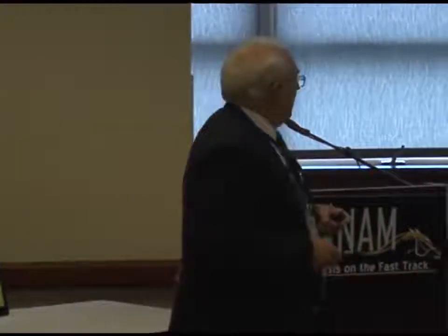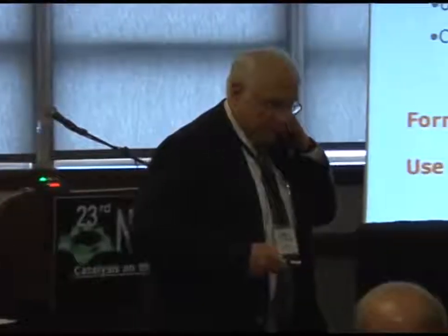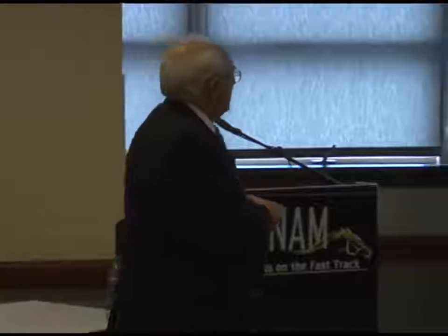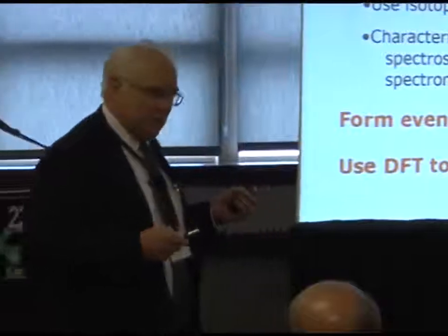Okay, let's now talk about some synthesis and some reactivity and so forth. So with any of the examples I've just shown, for example, a rhodium diethylene complex on zeolite HY, we can modify the ligand environment in a straightforward way. So if we start with ethylene ligands in flow CO, the CO replaces the ethylene like a shot because it's much more strongly bonded to the rhodium than ethylene is.